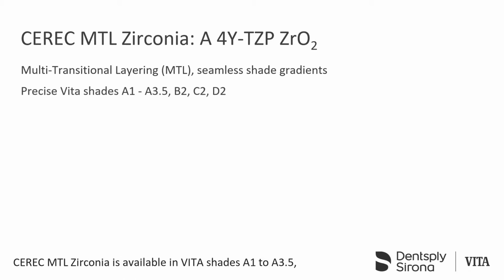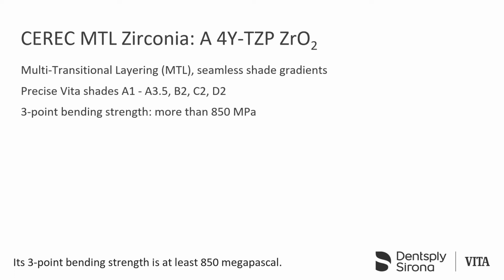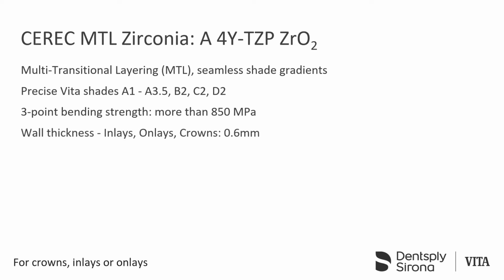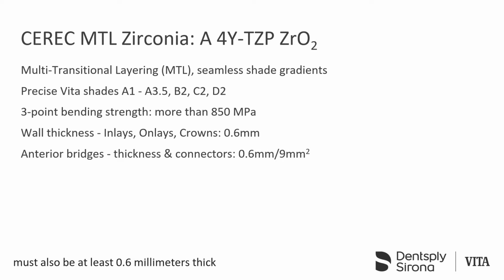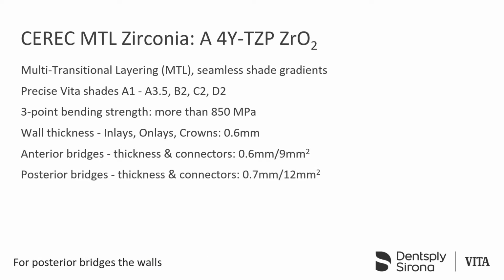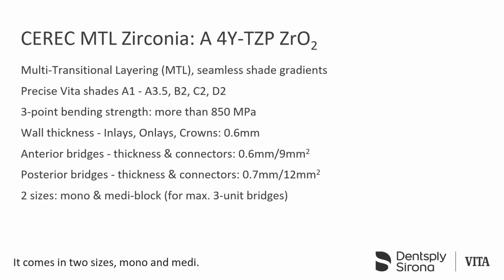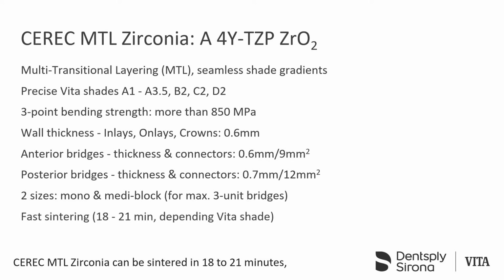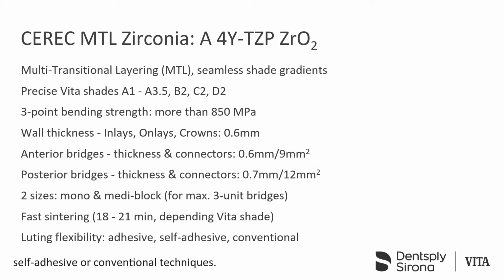CEREC MTL Zirconia is available in Vita shades A1 to A3.5, B2, C2, and D2. Its 3-point bending strength is more than 850 megapascal. For crowns, inlays, or onlays, the walls only need to be 0.6 millimeters thick. With anterior bridges, the walls must also be at least 0.6 millimeters thick, and the cross-section of the connectors 9 millimeters squared. For posterior bridges, the walls must be at least 0.7 millimeters thick, and the cross-section of the connectors 12 millimeters square. It comes in 2 sizes, mono and medi. CEREC MTL Zirconia can be sintered in 18 to 21 minutes, depending on the shade. It can be luted using adhesive, self-adhesive, or conventional techniques.